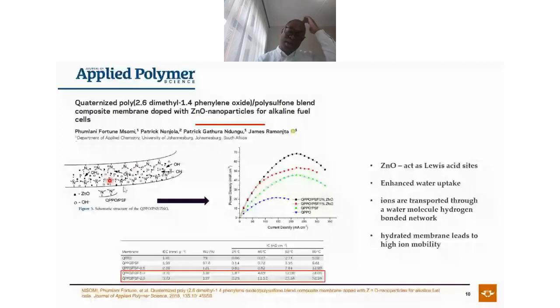Well, we propose that once we've done this system, if you're having the membrane system, you have these conductive sites, the nitrogen based, that's why we're calling it quaternized. And you have OH minus pass through. If you have zinc oxide, it can act as what we call a Lewis acid site, which means your OH minus is able to forge a path on the zinc oxide. So basically the pathway of your OH minus to transport from the right to the left, remember it's moving from this side to this side.